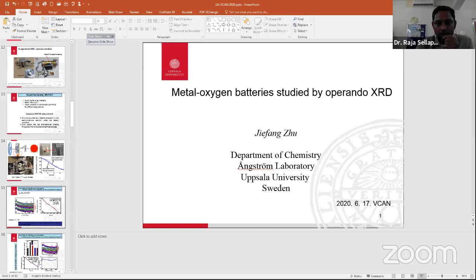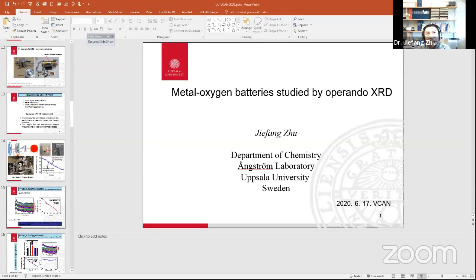Do these oxygen batteries have longer life than other batteries? Good question. When talking about long life, I would say no, because if you judge by the cycle number, it is far lower than the lithium ion battery. But if you judge by time, normally when we cycle this metal oxygen battery with very low current density, one cycle always takes more than 30 hours. In that case, you could see it as long. But if you judge by cycle number, generally we think it's short life.